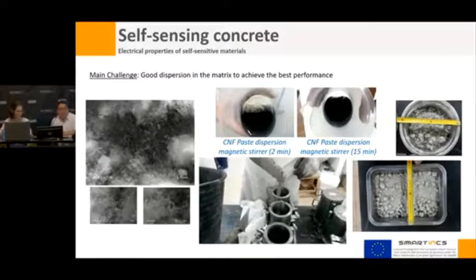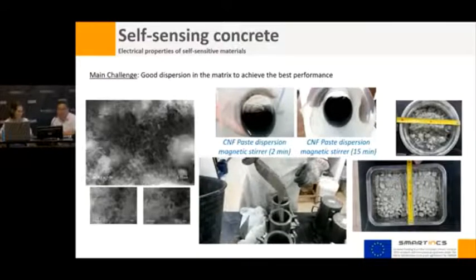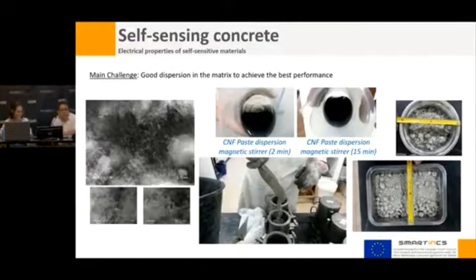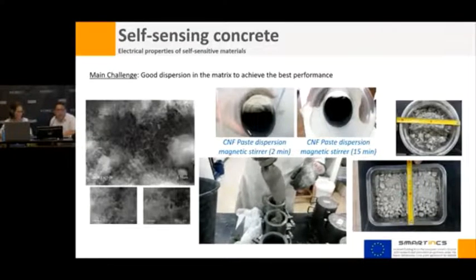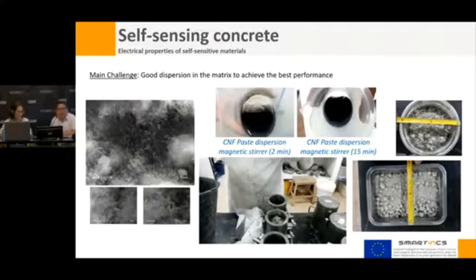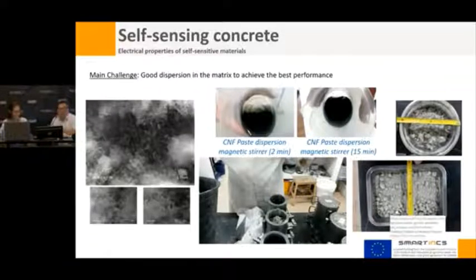There was one of the problems with this material. You can see we had to develop a concrete. It was very difficult because we worked with two kinds of carbon nanofibers and carbon microfibers. That was the difficulty. And we can see here the bundles inside the matrix. We worked with a low relationship between water and cement, and dispersion was difficult. One of the big problems of these kinds of materials.